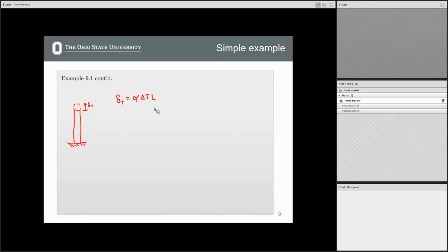Okay, but we do have a wall or a ceiling at the top. So then we can look at what would be the force required to take this bar and actually move it back down to this position. So this is going to be a delta force. That's basically balancing these deflections, not strains. So we have delta F, and these are established relationships, that delta F is equal to force times length over area times the Young's modulus. Now keep in mind, with just typical normal compressive stress, force over area is stress, right?